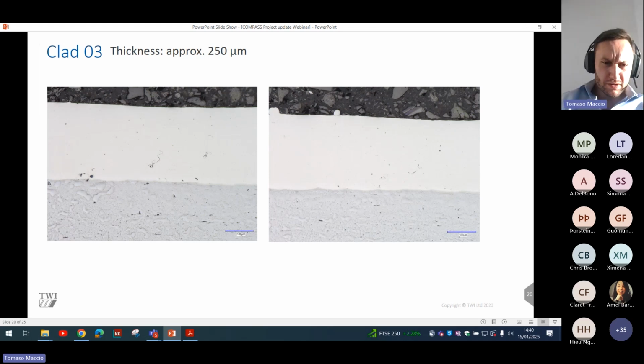So the defects are very, very minimal. We're getting around 10 micron defects on these samples, and the thickness is quite desirable. So we're getting a 250 micron layer thickness, which is really what we're trying to achieve.